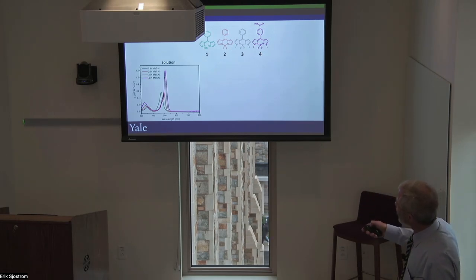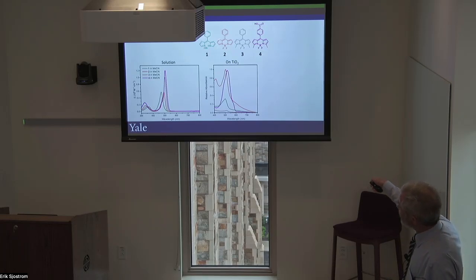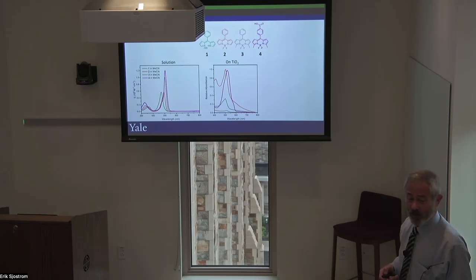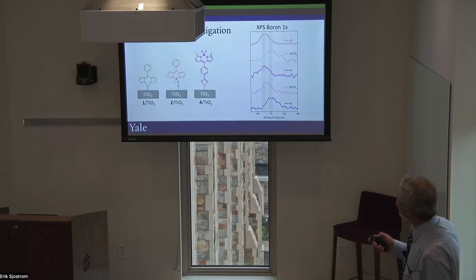So these are a series of molecules we looked at. This is the dipyrrin, this is the BODIPY, this is the fluorophore that's used in biology, which has a dimethyl substitution. And the reason nobody had found that it binds to metal oxides is that the dimethyl substitution blocks the binding. And you can see there's no binding of the dimethyl. But if you remove those methyl groups and remove the steric interactions, it binds just about as well as the carboxylic acid, where we now, with the dimethyl group, can't bind through this end, but it binds on the carboxylic end. This has been widely used in dye-sensitized solar cells because it binds and has nice interfacial electron transfer properties. And you can see that the BODIPY binds comparably well, which was really surprising to us. So that was something that we wanted to learn a little bit more about.